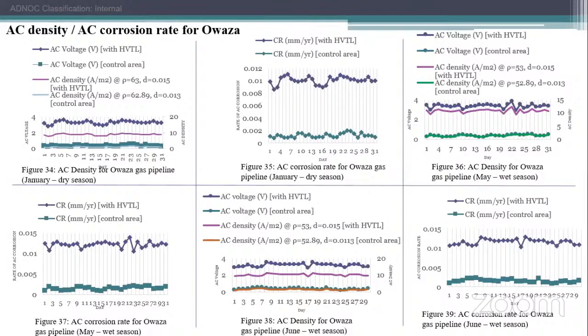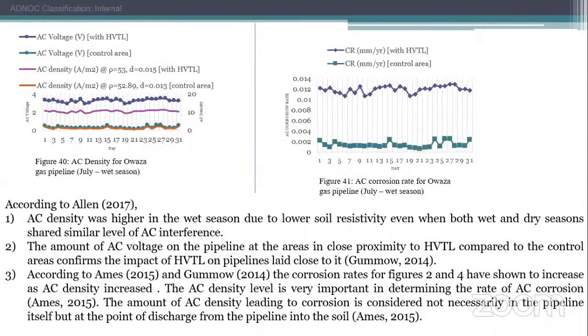So this is the AC corrosion density and the AC corrosion rate measurement itself. We can see that the AC corrosion density was higher in the wet season due to lower soil resistivity. The amount of AC voltage was measured for areas close to the high voltage transmission line and another control section, because we want to check if the high voltage transmission line had any interaction. So you do close to the high voltage transmission line, then you go some distance away also, so we can check if there is interference.